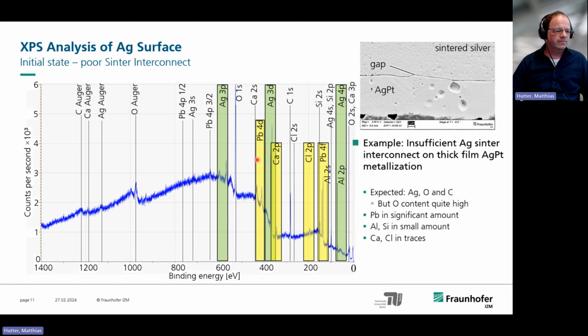You can also use it, as already mentioned, for the silver sintering. This is an example where we sintered on a thick film silver platinum metallization on a ceramic. This is normally done together with the thick film application with a sort of glass. And you see that in this case, some elements of the glass are really found on the surface. And these glass contaminations on the surface prevented us from getting a proper joint.